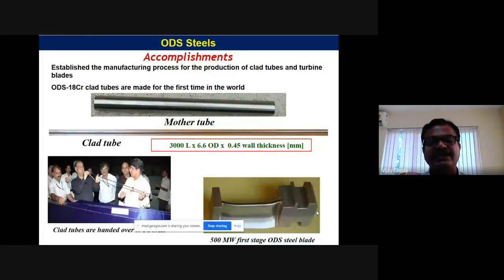And you could always see that from the extruded rod, a mother tube is made, and then from that the clad tube, and this is what we have handed over to IGCAR for practical applications. And then these tubes will now be used in Bhavani, the first commercial fast breeder reactor, which is coming up and will be commissioned by the end of 2021. So that is where these clad tubes will be used. And turbine blades are also made and given to BHEL, and they are testing these blades before they are being used.